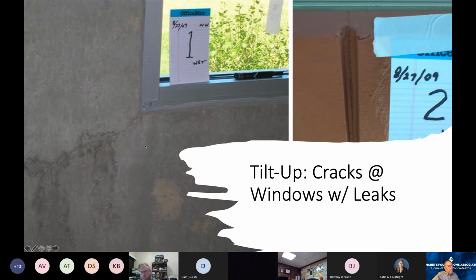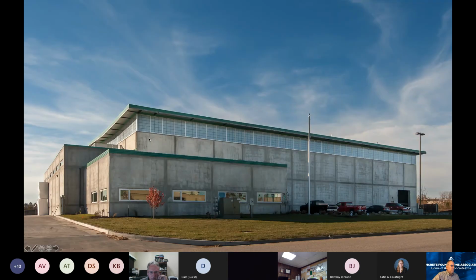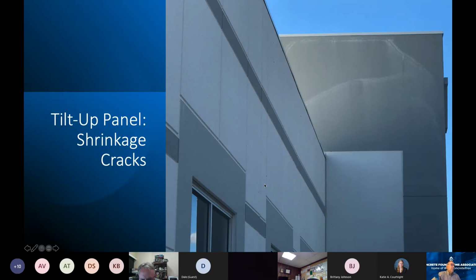Similarly, on this reentrant corner, when we did rebar analysis, we found that the reentrant bar crack control was about 3 inches off the corner where it should have been 3/4 of an inch off the corner. And so they had no chance to control this crack from the beginning. There's a larger image for you of that reinforcement mat pattern cracking of that project that they ended up sealing. This is not long after a rain, so the cracks are really showing nicely there, but like I said, they sealed it and are very happy with it. They still haven't painted the building.